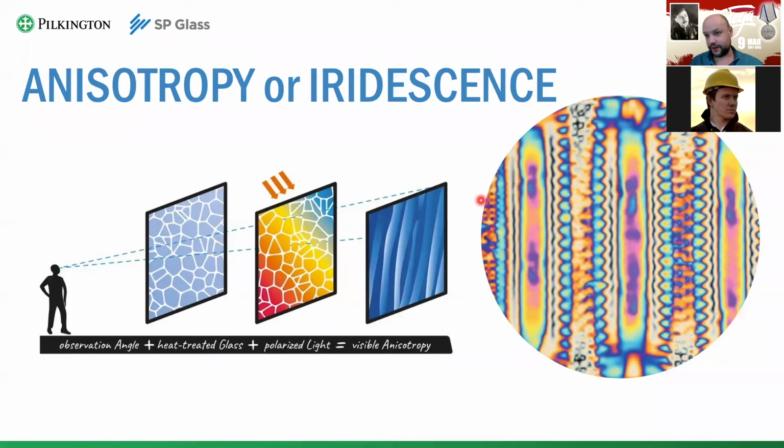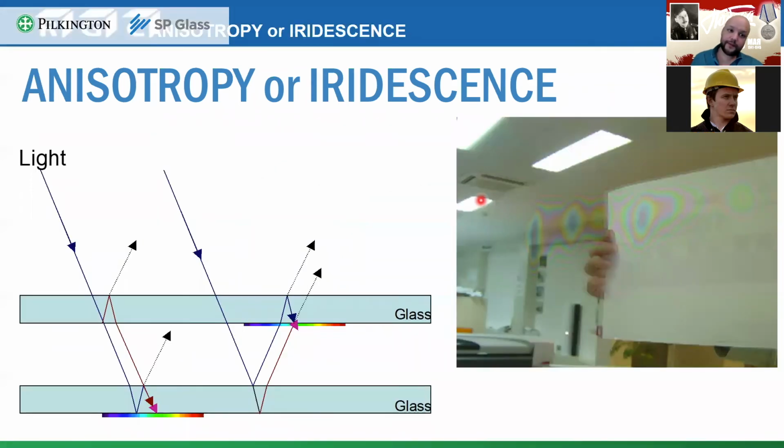This doesn't affect the physical properties of the glass by a lot because it is tempered anyway. There is slightly different stress we are looking at when we talk about the ability of the glass to withstand loads. But on the surface, the stress distribution is anisotropic. So what do you have? Because of this anisotropy, you have anisotropy of the glass refraction index.